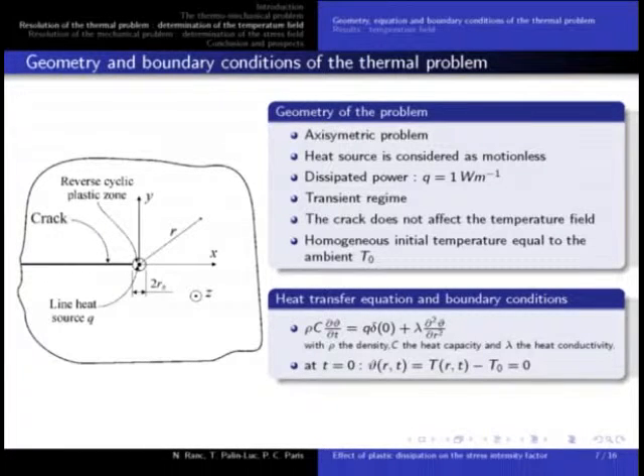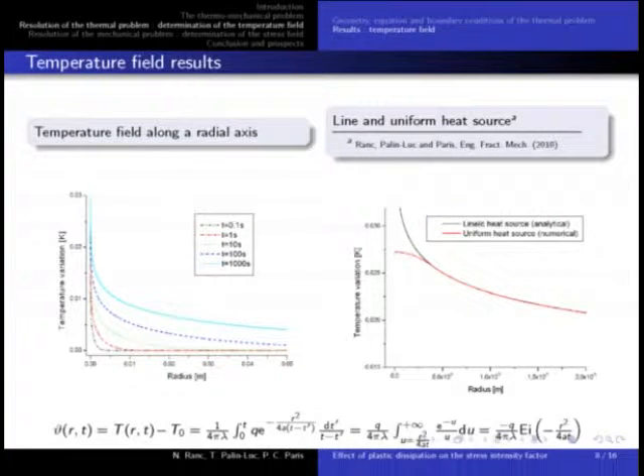We consider the transient regime. It means that when the crack starts to propagate, what happens and how the heatings appear. And for the temperature effect, in first approximation, we consider that the crack does not affect the temperature field. This is a strong approximation maybe, but for future work in finite element analysis, we can take into account the effect of the crack on the temperature field. So if we write the heat transfer equation, we have this equation with the local heat source, with the Dirac function here. And we are looking for the temperature variation field with a first homogeneous temperature T0.